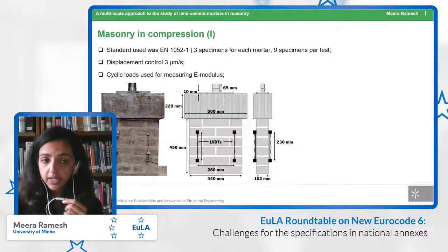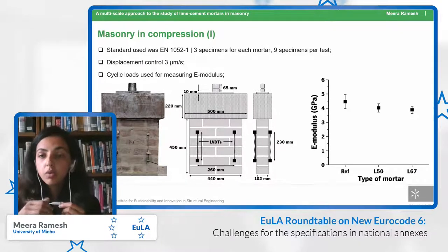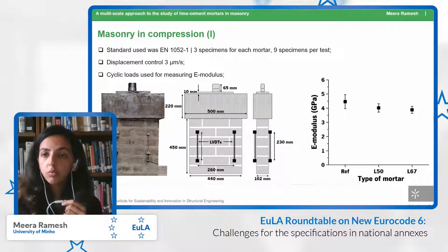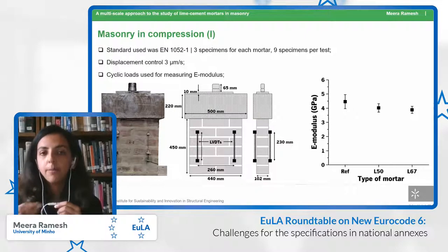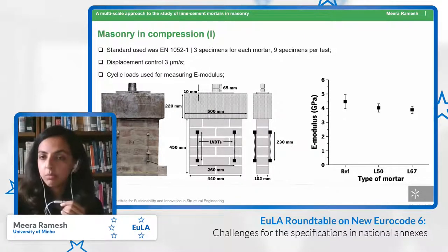We also used cyclic loads in the same setup that is shown on screen. And we found that once again, if you use a mortar with lower stiffness or lower strength, the Young's modulus of masonry is lower. But they seem to be in the same range once again.